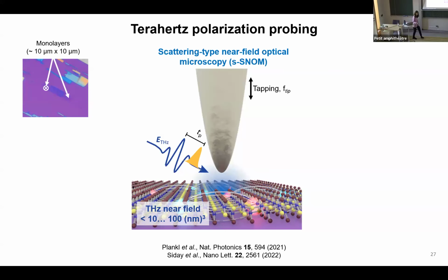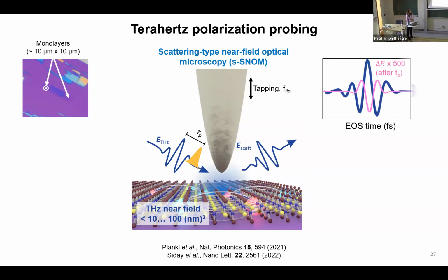There are even commercially available instruments, or people etch their tips in the laboratories. They can get very, very sharp tips, so we can gain information about really nanometric or micrometric regions of the sample. Now, what we do is shine terahertz radiation on our material, and we study how it scatters to the far field, and we run our oscilloscope of light. This scattered far field will contain information about the nanoscopic region of the sample, in our case the monolayer of chromium sulfide bromide, which was very small. And then we can also study the pump-induced change in this scattered terahertz radiation in the presence of excitons.